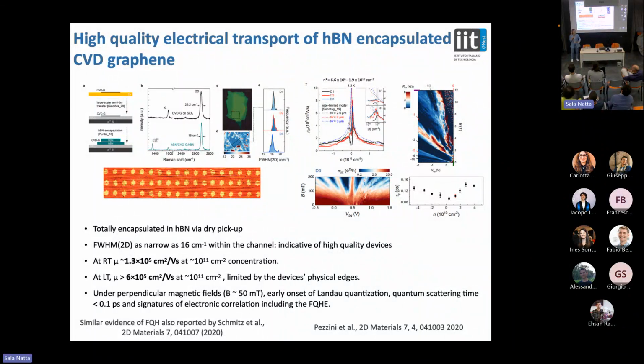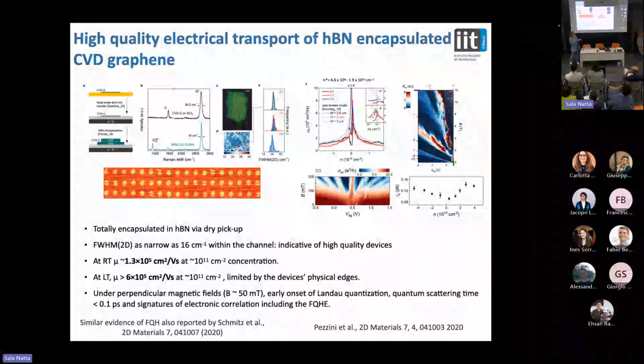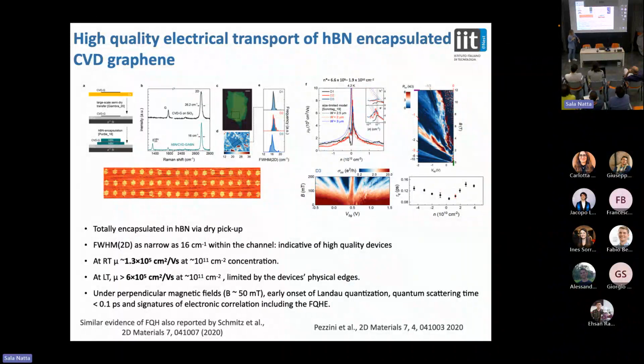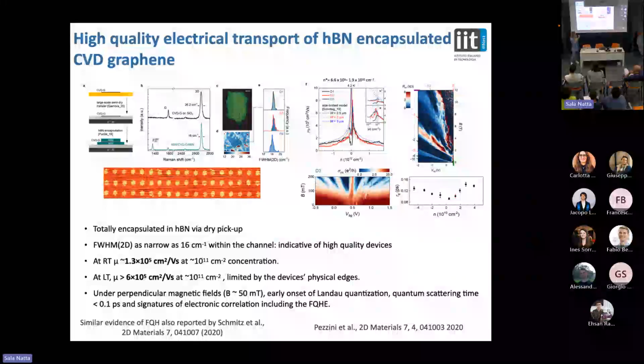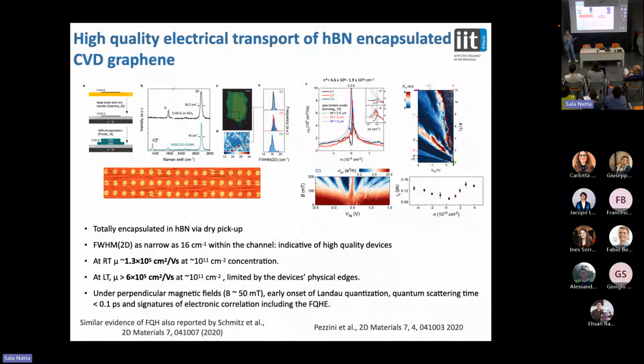Boron nitride is an insulator, completely an insulator. So basically, you can start to think about making 2D electronics, only with 2D material, which will be transparent, flexible, and everything else. So in this case, if you use this kind of sandwich technique and you put graphene together with boron nitride, and they're very flat, they don't have strain inhomogeneities, they all match each other, then the mobility is those 600,000 that I was mentioning.